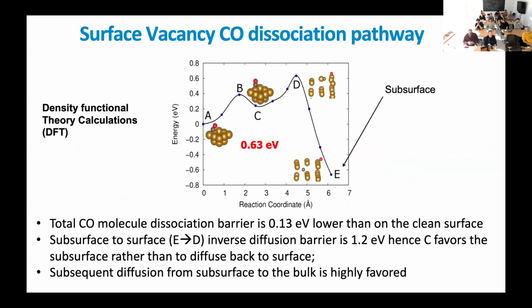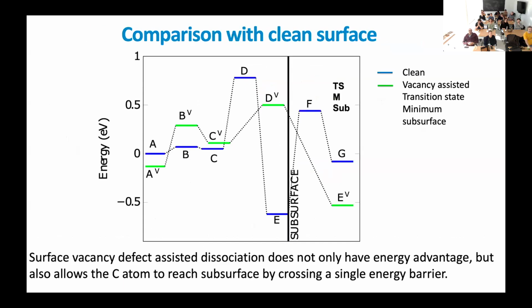And in this case, you see that the landscape really has changed. So we have multiple barriers. Okay, so the pathway from A, B to C, and then C, D to E, and so on. But you see that the barrier in the presence of the vacancy is smaller. But what is also very important is that we have, in addition, a diffusion of carbon to the subsurface. Okay, so we start to see the ingress of carbon into the subsurface. So this is just to give you an idea of the diffusion pathway that we could find using DFT calculations, okay, for two different scenarios, in the presence of a vacancy and without the presence of the vacancy.